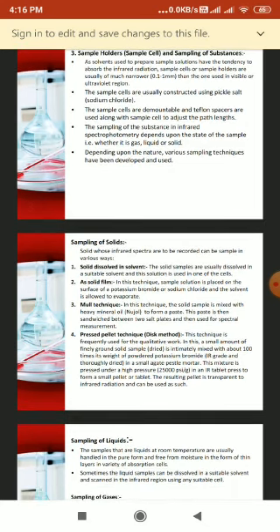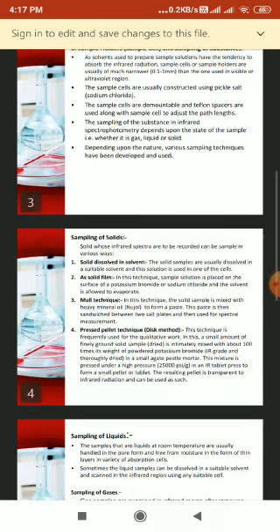Third way is the mull technique. In this technique, the solid sample is mixed with heavy mineral oil, meaning Nujol, to form a paste. This paste is then sandwiched between two salt plates and then used for spectral measurement. Although Nujol is transparent in most parts of the infrared region, it has absorption maxima at 2915, 1462, 1376, and 719 per centimeter. This is the drawback in using Nujol for certain compounds which may have absorption in a region similar to Nujol. This technique is mostly used for qualitative work and not for quantitative estimations.